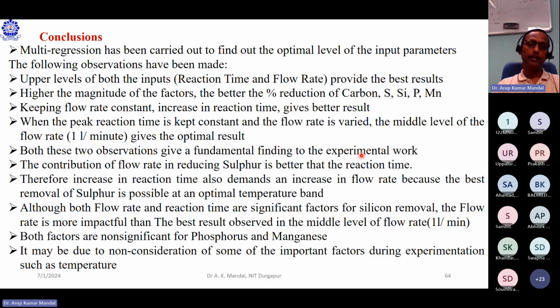From this multi-regression analysis model, we can conclude that the conclusion from the experimental data is validated. The upper level for both inputs, reaction time and flow rate, provides the best result. But the higher the magnitude of the factor, the better the percentage of reduction in the case of carbon, sulfur, silicon, phosphorus, and manganese. When we keep the flow rate constant and increase the reaction time, it gives a better result. When the reaction time is kept constant and flow rate is varied, the middle level, 1 liter per minute flow rate, gives the optimum result. Both these observations we have already seen in the fundamental findings of our experimental work.